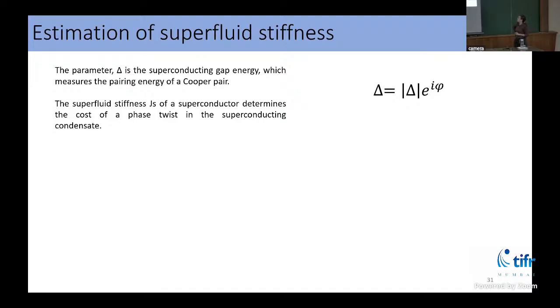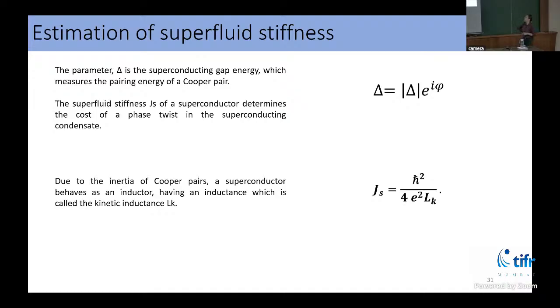So this superfluid stiffness is the energy cost required for twisting the phase in the superconductor. And that itself gives me more additional information about a superconductor than just my critical currents and critical temperatures, which give me a more direct estimate for delta. And it so happens that due to the inertia of the Cooper pairs, a superconductor behaves like an inductor, and this inductance value is related to the superfluid stiffness. Now, an estimate of this superfluid stiffness would give us insight about what this inductance is and also about the symmetries of the order parameter.